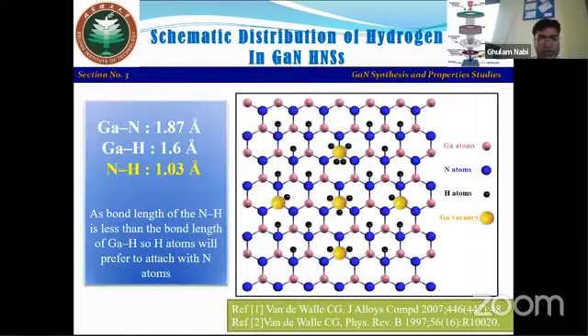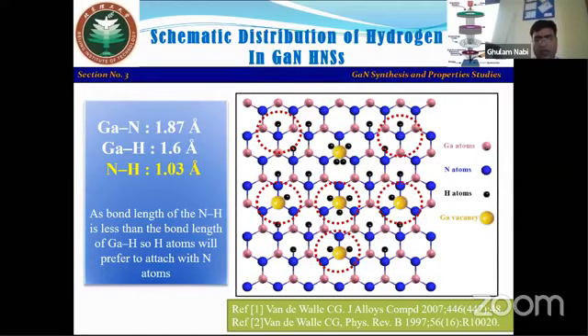Here is a little bit about the mechanism of the absorption system, in which we can see that at different places, the gallium vacancy places, 1, 2, or 3 hydrogen atoms can be stored. How can we see that these are stored at the gallium vacancies?